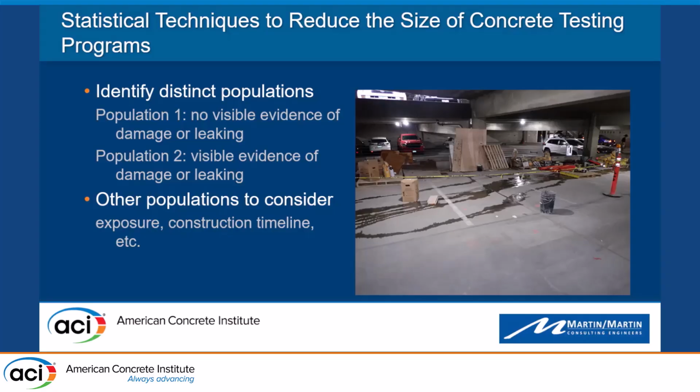Exposures, different populations, right? The roof level that's exposed to weather is different than the first level that gets all the cars that drive in and shake off all Denver's mag chloride onto the parking structure. And then I've got intermediate levels that are away from both those exposures. This photo happens to be at an intermediate level, and snow melt off one particular car is coming down the ramp and saturating the construction joint that we're concerned about while we're out there fixing it.